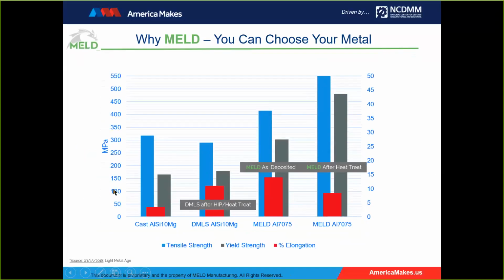The next slide is very similar, the same cast, the same powder bed, AlSi10, and now you see that same 7075 as deposited and after our heat treat. So again, in many cases, our as deposited mechanical properties meet the mechanical properties without a need for a heat treat. And if we want to bump it up, we can use our own custom blends of heat treatments to improve the mechanical properties. So again, a quick overview, you choose your metal, and here's a comparison of other technologies to say that as deposited or with a heat treat.